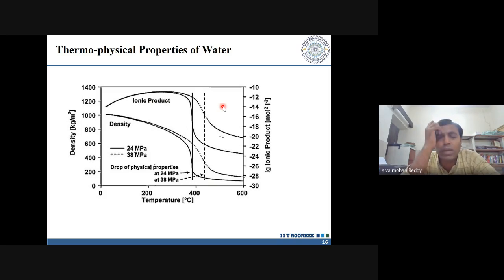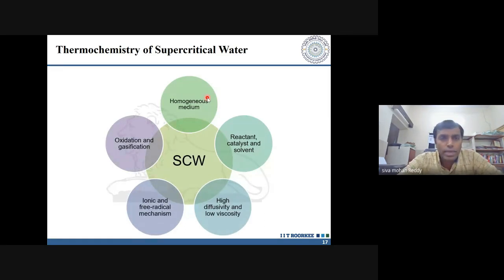The ionic product means it is effectively able to generate ions like hydronium and hydroxyl ions at the critical point conditions. The generation of these ions enables it to act as an acid base catalysis. So that's the reason why you see supercritical water or near critical water, at the conditions you maintain at the critical point, generating acid base. These acid base can act as a catalyst and improve your hydrolysis reactions, so that you would be able to degrade the biopolymers like cellulose, hemicellulose, and lignin into their respective components, and these components will further degrade in the presence of ions or radicals, depending upon the operating conditions we are choosing. Okay, so now if you look at the thermochemistry, I'm just summarizing it.